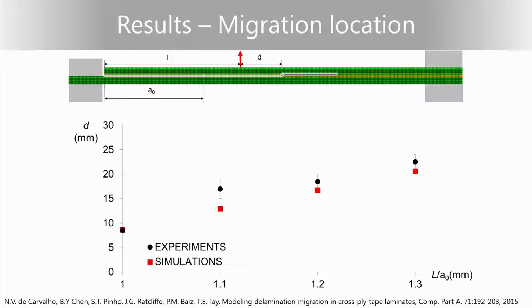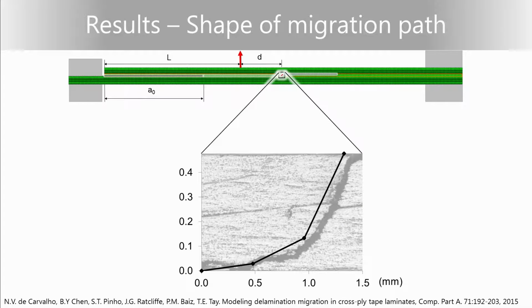In the vertical direction, the distance d at which the crack migrated from one plane to another. You can see the simulations in red and the experiments in black agree very well. If we look now at the shape of the migration, I'm superposing our predictions with an actual micrograph of that migrating crack, and you can see that we have a very similar shape. So that was two-dimensional and static.